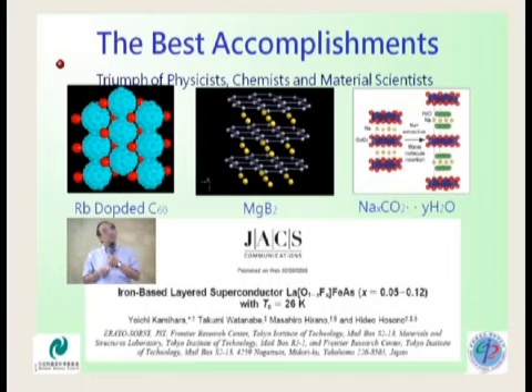And the most surprising was in 2001, I think, Professor Akimitsu in Japan discovered an existing compound, the so-called diboride, MgB2. Dr. Yang is one of the experts in that, Professor Yang, the chairman of this particular session, and it also shows very interesting superconducting properties with a TC around 40 Kelvin, okay? And I'm sorry, this is cobalt oxide, not the copper oxide, not the oxygen, okay? It's a cobalt O2.